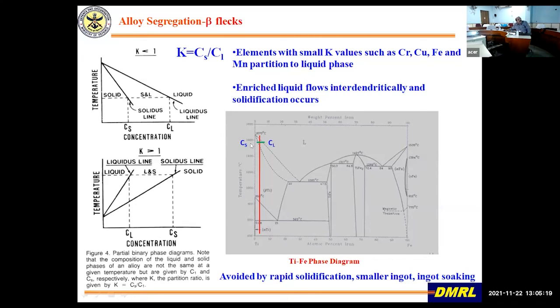Now, this is the titanium-iron phase diagram. You can see this is a deep eutectic. So this is Cs, this is Cl. So iron gets rejected into the liquid, and you have segregation of iron. In certain regions, you have preferential iron, and that causes problems. So this can be avoided by rapid solidification, a smaller ingot, and ingot soaking.